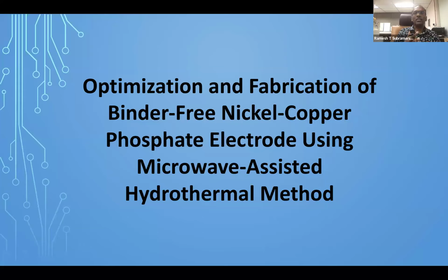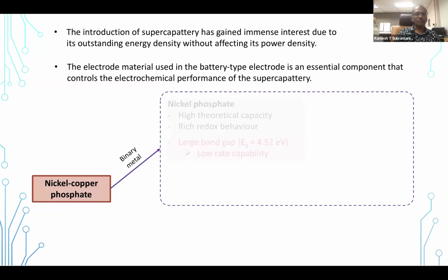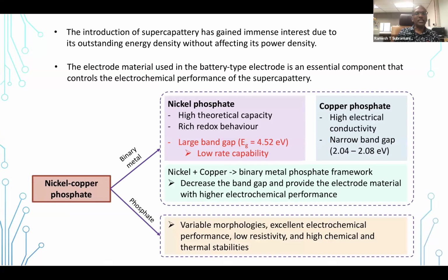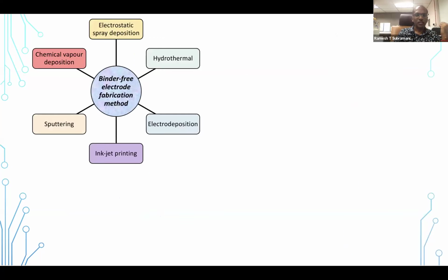We also did the optimization and fabrication of the binder-free nickel copper phosphate electrode using a microwave assisted hydrothermal method. The reason we are using nickel copper phosphate is that this combination gives us a binary metal phosphate framework, which decreases the band gap and provides the electrode material with higher electrochemical performance. And the phosphate gives excellent electrochemical performance together with low resistivity and high chemical and thermal stabilities.